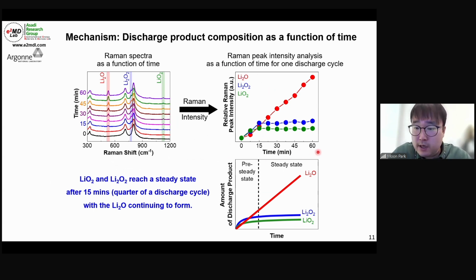And then this is the plotted figure. You can see that from the start of the discharge to 15 minutes, all the discharge products increase, looking linear. But after 15 minutes, the lithium superoxide (green) and the lithium peroxide (blue) did not increase at all, staying almost the same. But the lithium oxide, Li2O, increased linearly.